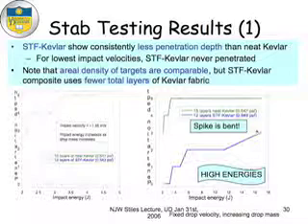So at low energies, what we find is that 15 layers of Kevlar is very easily penetrated by that ice pick, just as you saw Renee do on MBC-10. You know, she stabbed right through it. On the other hand, if I take 12 layers of the treated material that has the same weight as the 15, at low energies, there's no penetration. And at higher energies, as we drop it from a higher height or we add more weight to the spike, eventually the spike is bent. Here, by the way, once you get through 5, we stop counting because you're probably dead, so you don't care.